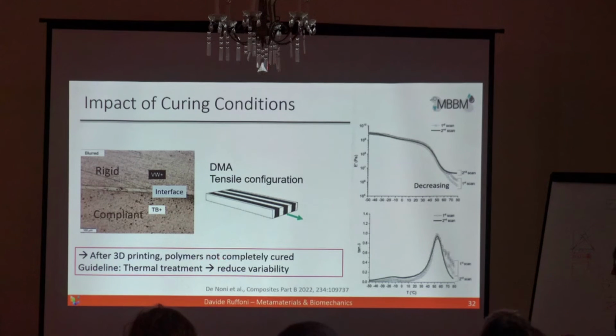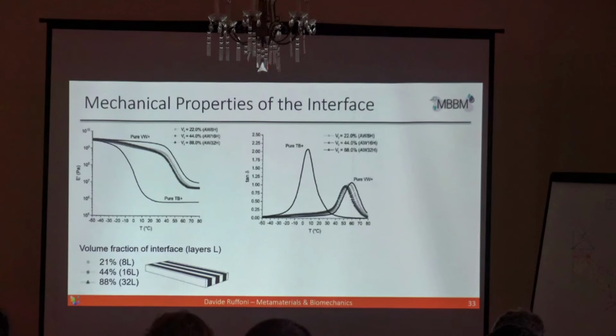So the polymers are not completely cured, and this is a side comment for those techniques: if you do a thermal treatment after printing up to 80 degrees, you will reduce a lot the variability of your test. This is something that we were a little bit surprised by.